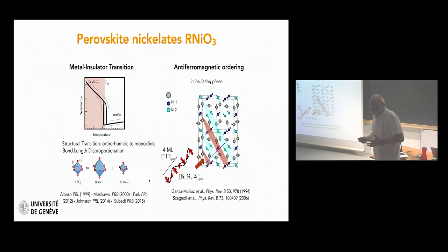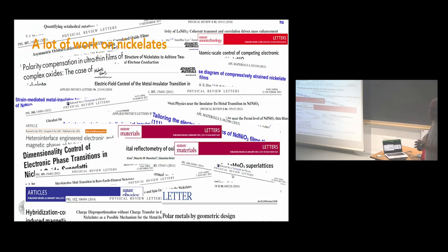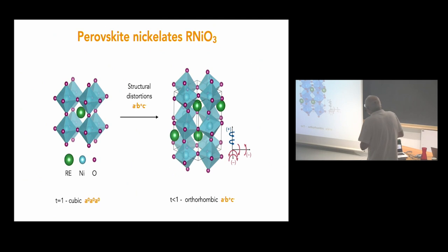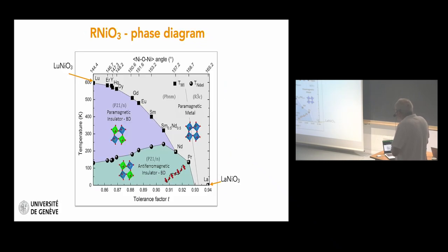And these materials have been the subject of very, very many studies, and there are millions of papers on nickelates. Obviously, I will not be able to tell you about all this. The structure, as I said, the nickelates are orthorhombic with this particular rotation pattern A minus, B plus, C minus. The phase diagram that you already saw yesterday is shown here. Temperature, tolerance factor, or nickel-oxygen-nickel bond angle.